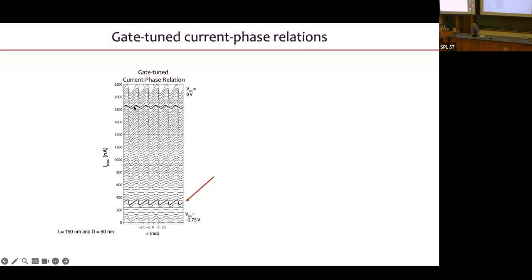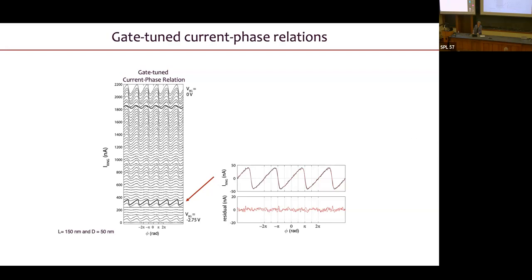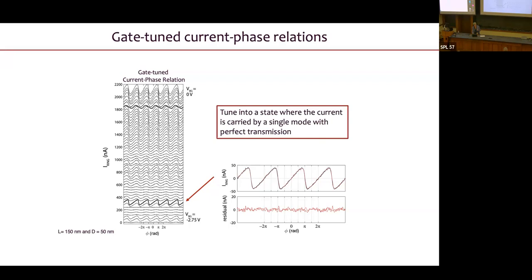So again, this is the part of the talk that's really for the experts. But if you look at, for example, this mode, you can see that it very beautifully fits the Beenakker formula for transmission through a single mode with high transmission at a very small but still finite temperature. So that means that we can tune this into a state where the current through the junction is carried by a single mode with perfect transmission. And I thought that was pretty cool.